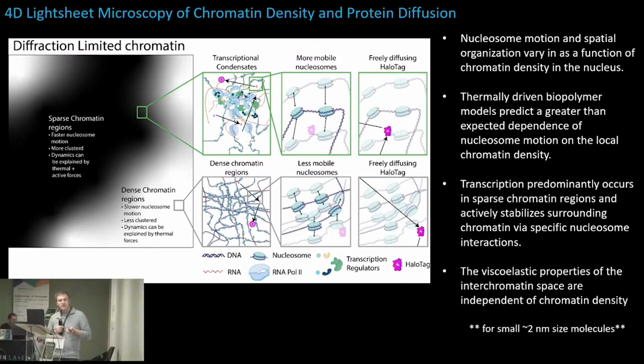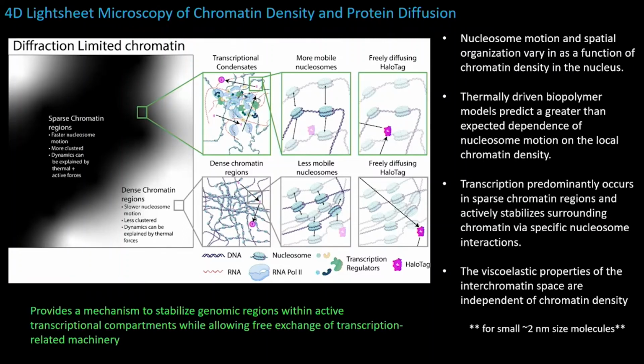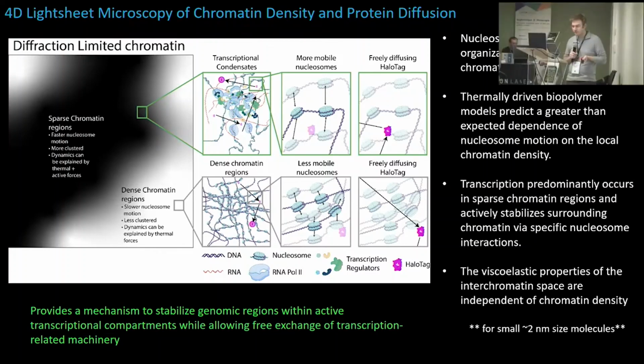What's interesting is that the viscoelastic properties of the interchromatin space appear to be completely independent. So it's not like they're just making a stickier, more viscous thing and that's tethering everything together. For a freely diffusing molecule, it seems to be completely agnostic to the chromatin density. And that would just say, well, the nucleus is full of a lot of other things besides chromatin: RNA and other nucleic acids and other proteins. So the viscoelastic properties appear relatively constant. But this is one way that provides a mechanism to stabilize genomic regions in these active compartments through a nucleosome-specific stabilizing effect, potentially through things like BRD4, bromodomain proteins stabilizing acetylated histones. But it doesn't actually seem to reflect any fundamental change to the viscoelastic properties in these different chromatin environments.